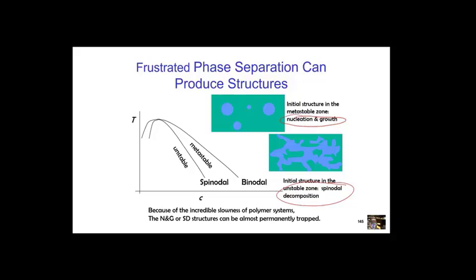Totally different structures, totally different properties. A lot of surface area in this spinodal decomposition, kind of this interpenetrated structure. Sometimes you can imagine taking one of these phases, say the blue one, and heating it up until it's sintered out, and then you wind up with this open, porous, spongy type network. So this is a way of getting structure into polymers, which, as molecules, often have this flexible structure with no order, but we've now seen that they can crystallize, and then the phase separation itself can lead to structure. That's kind of a neat thing. And we'll see echoes of this in other materials.